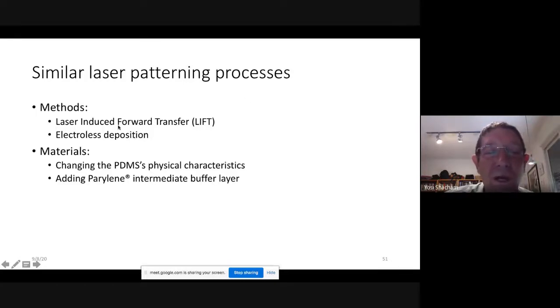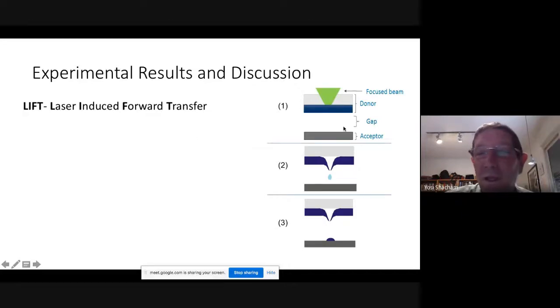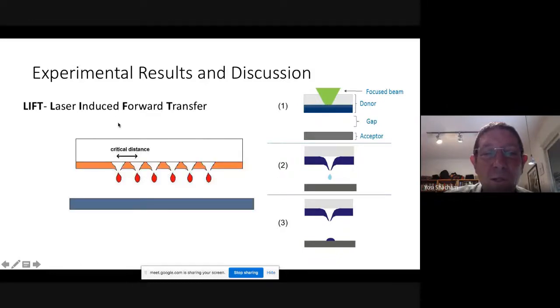So we looked at we have a laser, and there is a technology called LIFT. And LIFT is the following. You take the glass, you put a glass, on the glass you put the metal. And then you are illuminating from the backside with a laser. And because you illuminate it from here, you are generating a drop, and the drop is going down and deposited on your substrate. So you go to a different point and deposit another drop. And then deposit another drop. And then you can make an electrode.